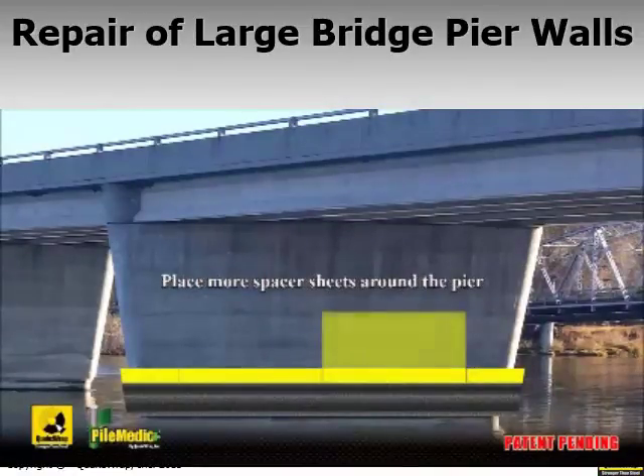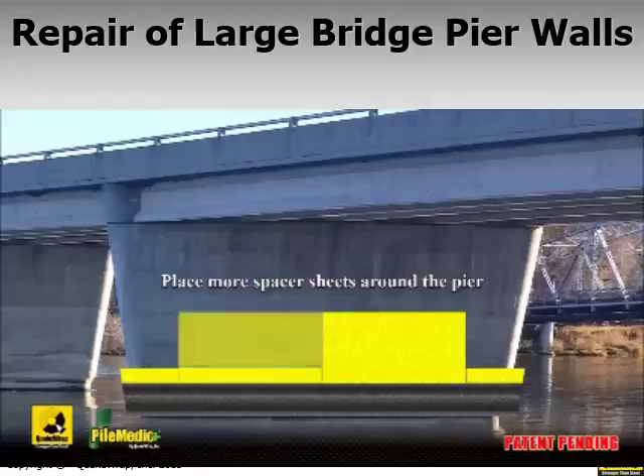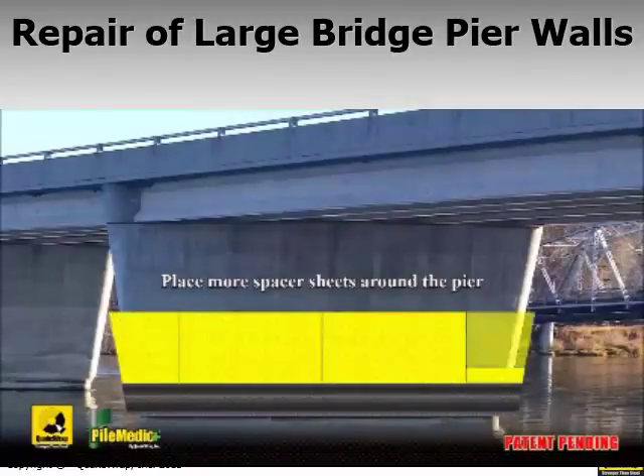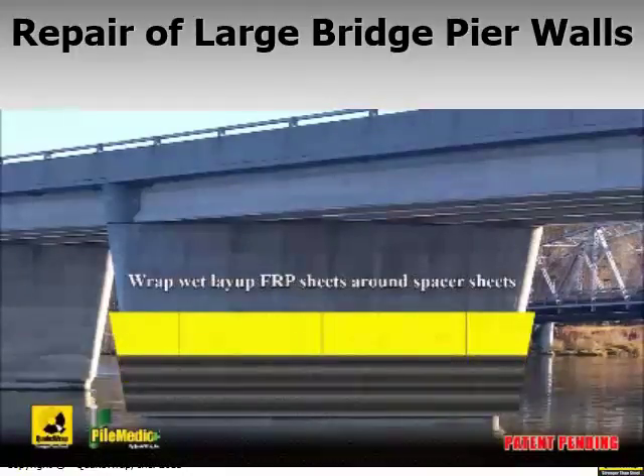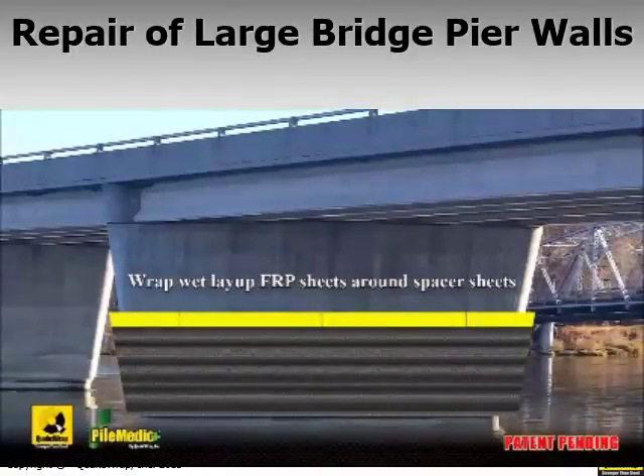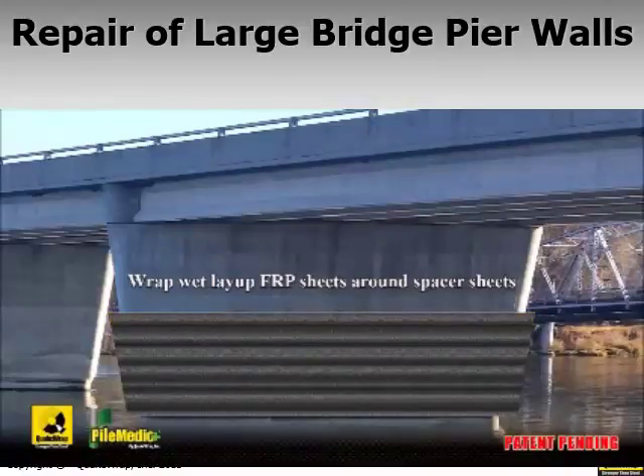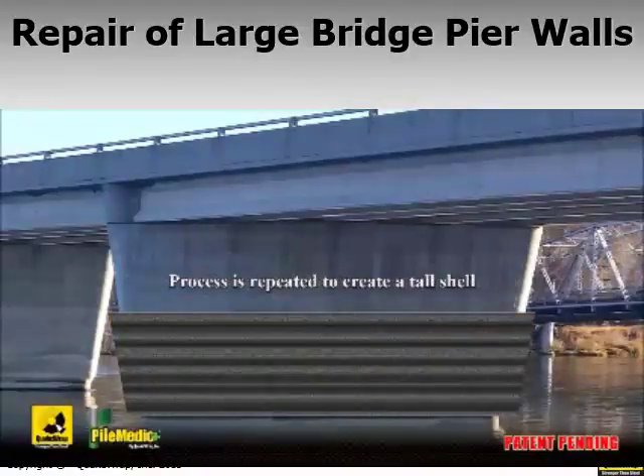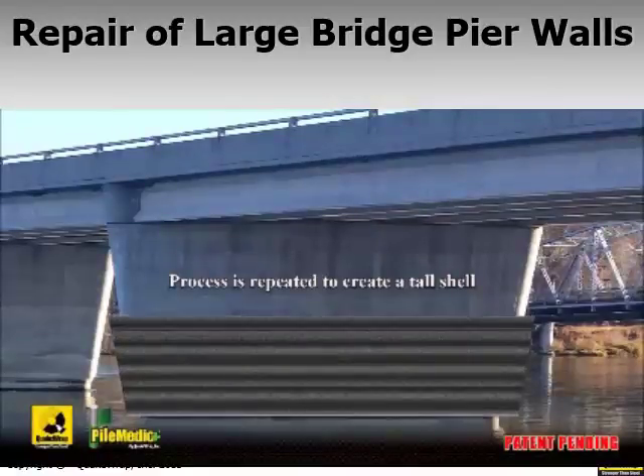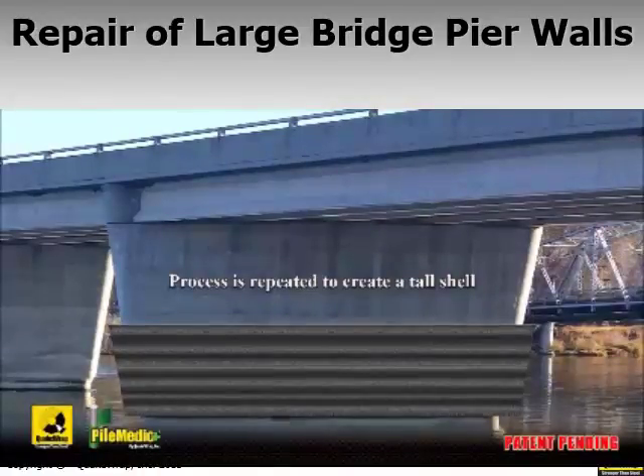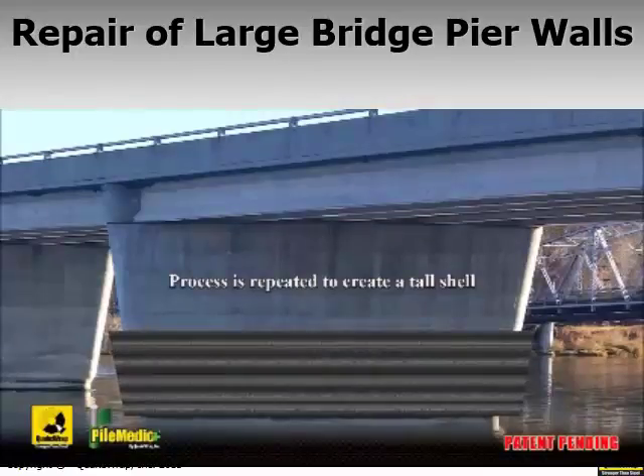Next, additional spacer sheets are added. These spacer sheets can be connected together and to the previously installed spacer sheets using adhesive or screws. Additional wet layup FRP fabric bands are wrapped around these recently placed spacer sheets. The above process is repeated as many times as required until a sufficiently tall shell is manufactured. In some cases, this shell may be long enough to reach the mudline at the bottom of the sea or river.